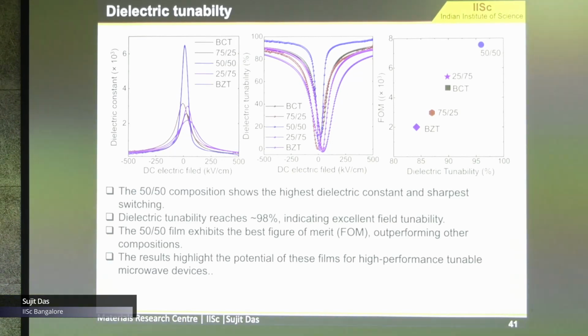So that could be used for many different types of applications. And we also calculated the figure of merit, which is basically the tunability divided by tan delta. And we found this 50-50% has the highest tunability, which has very potential applications, one maybe the microwave devices.